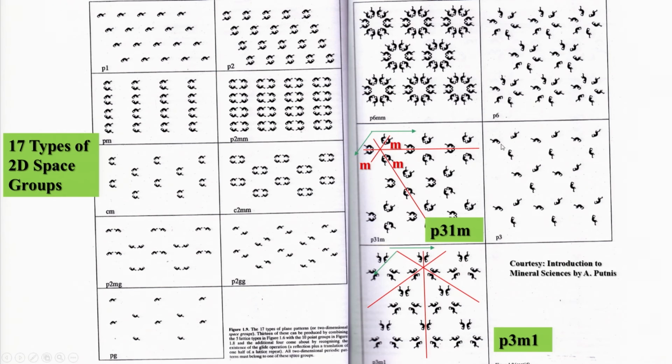So, what you have here? If you have a 3-fold axial symmetry here and a starting dinosaur motif here, a 120 degree rotation will put this dinosaur here, another 120 degree will put it here and another 120 degree will put it here. And if it is translated along the A direction, you can also translate this pattern along this direction, which is also of the same length A, and if this angle is 60 degree, you generate this pattern here.